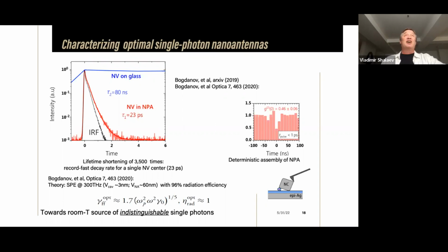Typical lifetime is nanosecond. With, per cell, let's say 10,000, you would beat the decoherence time by a factor of 10. And for that, we are now looking at other types of single photon emitters, such as germanium or silicon vacancy, or hBN centers, which in this case, the gap would be even smaller and the enhancement would be particularly strong. And that in principle could enable an exceptionally important thing: first demonstration of room temperature indistinguishable photons.